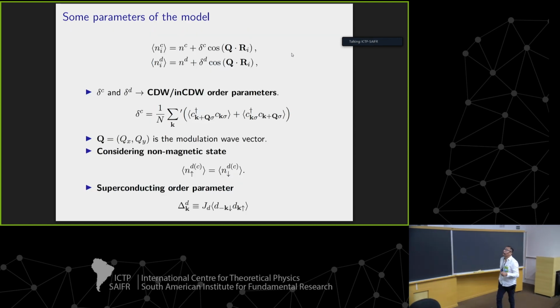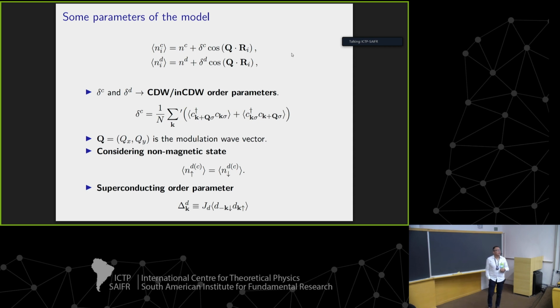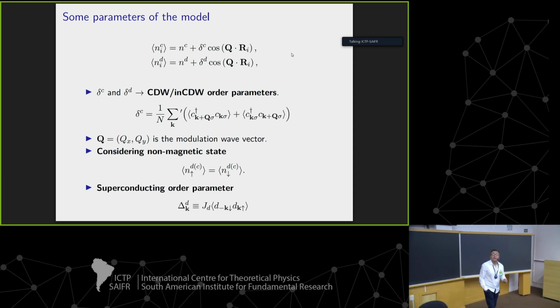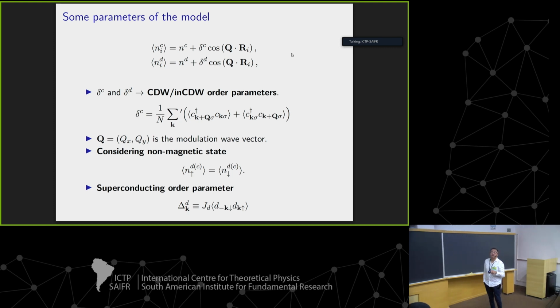Square lattice. Okay, some parameters of the model. We introduce a charge density wave order parameter from this average value of the electron C and D. Okay, this delta C or delta D are the CDW order parameters. This is the equation for this order parameter.